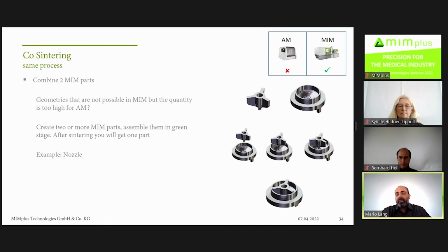So what we have done now, we have built a tool with 2 cavities. So the right part and the left part. And after the injection process, we take those parts and we assemble them together. We have a press fit in the green stage. Once they are assembled in the green stage, we go through debinding and sintering. And during sintering, those parts are connected. The traditional way would be you have 2 parts and you assemble them by laser welding.